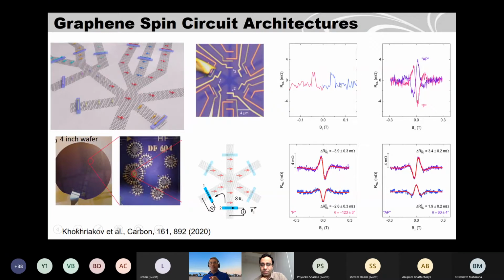But you don't see the complete picture here because this is showing a projection of the spins, because this is at some angle, and whatever spins are at this angle, you will see that. Okay, so it's a projection of the spins you inject onto the detector magnet. You don't see the complete magnitude here. But in Hanle, you can see the complete magnitude. But it has different components, like symmetric and antisymmetric components, because it's non-collinear. Very interesting structure. Any questions?